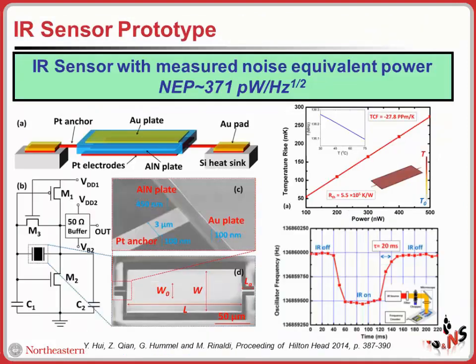We also connected this device to a low power CMOS oscillator. This was built in the 0.5 micron CMOS process. In this particular case, the power consumption was on the order of a milliwatt. And we characterized the thermal sensitivity and the noise performance of this oscillator, and we were able to extract a noise equivalent power on the order of 300 picowatts per square root of Hertz.